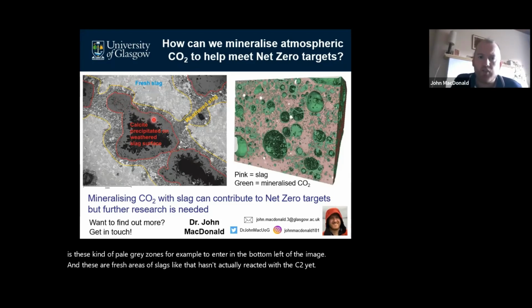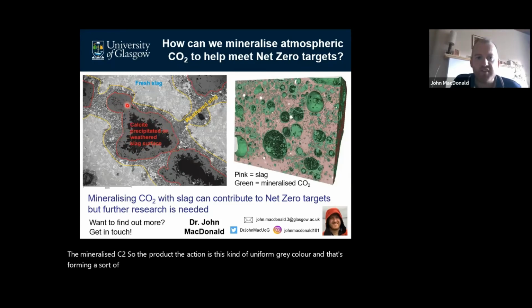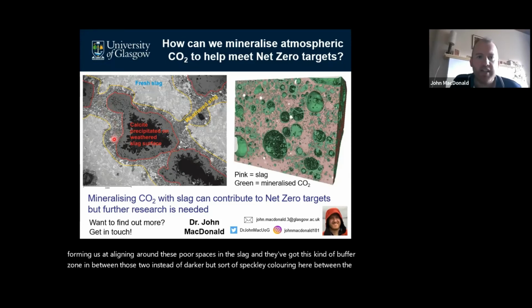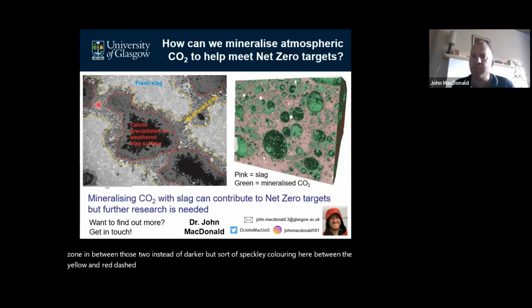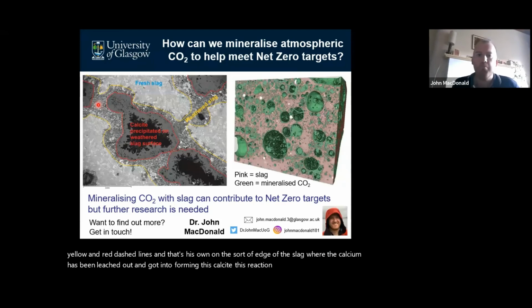The mineralized CO2, the product of the reaction, is this kind of uniform gray color, and that's forming a lining around these pore spaces in the slag. And then we've got this buffer zone in between those two, this darker but speckly colouring here between the yellow and red dashed lines. And that's a zone on the edge of the slag where the calcium has been leached out and gone into forming this calcite, this reaction that we saw in the previous slide for mineralizing the CO2.